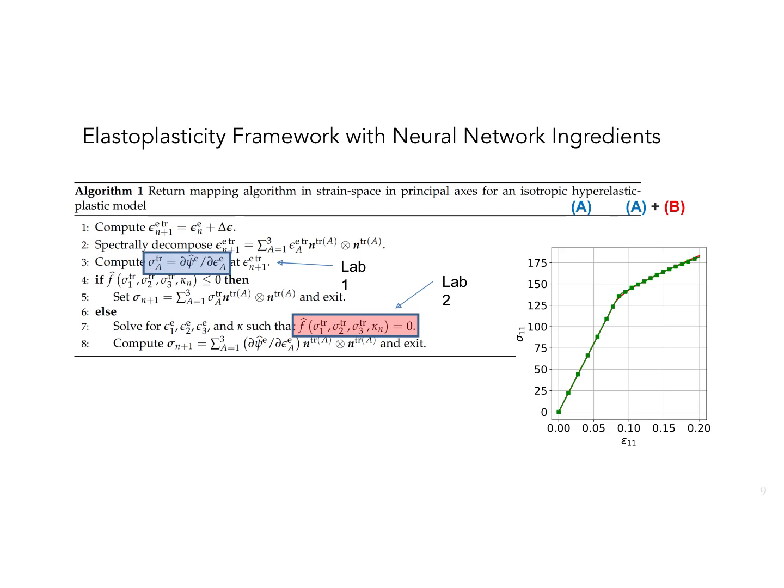This is what happens in an actual computer algorithm. I have the elasticity. In this case, I first compute the partitions, assuming that all the strain is elastic. I may decompose it with the eigenvalue and the eigenvector, or we don't have to do that if you don't want to do it in principal stress.